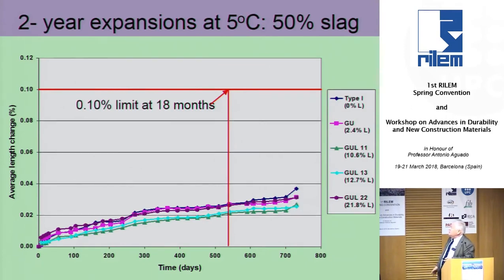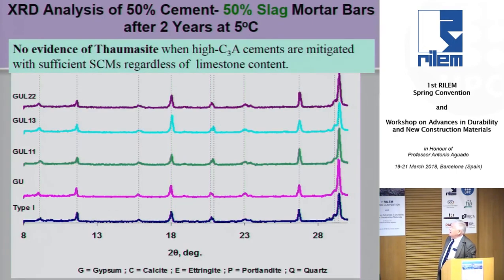And again, this is the sort of expansion we would see if you have sufficient replacement with slag. Our expansion limit is up there, the red line here, but our expansions, regardless of limestone content, are essentially the same. And when we have 50% slag in there and they're totally mitigated, again, it doesn't matter how much limestone, and we're not seeing any evidence of Thaumasite formation.